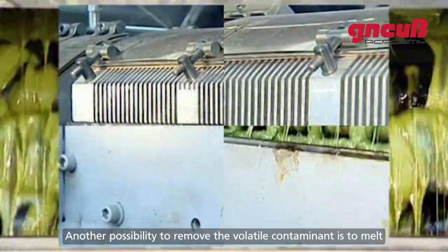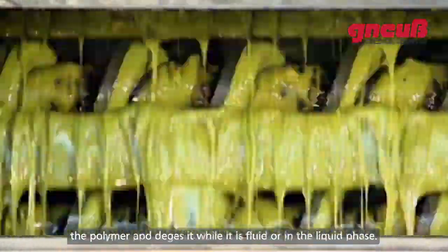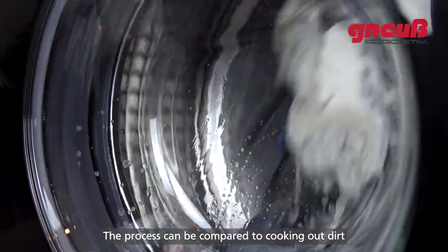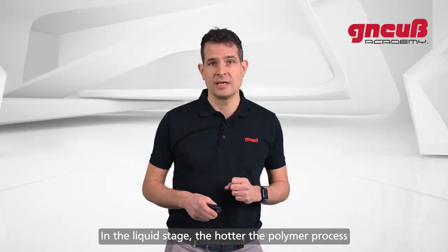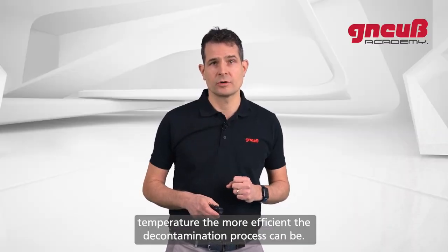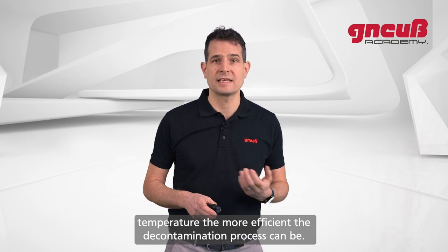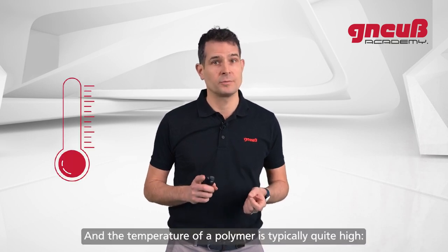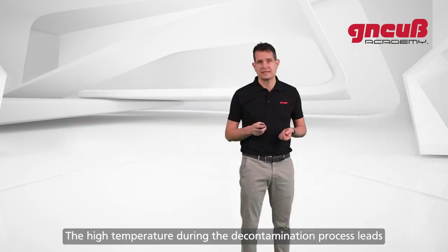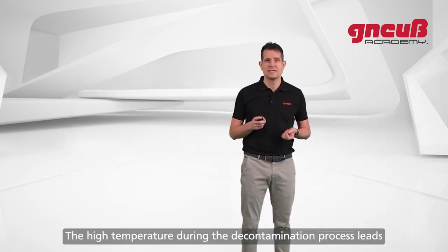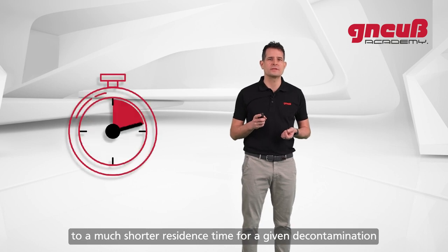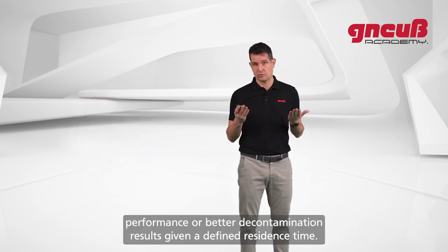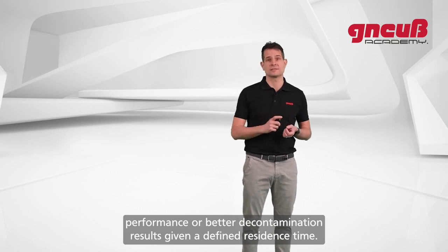Another possibility to remove the volatile contaminant is to melt the polymer and degas it while it is fluid or in the liquid phase. The process can be compared to cooking out dirt or odor from clothing. In the liquid stage, the hotter the polymer process temperature, the more efficient the decontamination process can be, and the temperature of a polymer is typically quite high. E.g., for PET, a typical processing temperature would be around 280 degrees Celsius. The high temperature during the decontamination process leads to a much shorter residence time for a given decontamination performance, or a better decontamination result given a defined residence time.